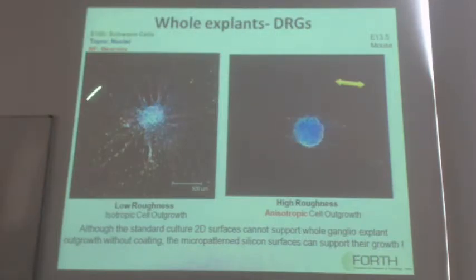You can see here in the low roughness we have an isotropic cell outgrowth of the neurons that can grow out of the explant. It's not very well visible, but you can see it later. Here you can see that in the high roughness surface you can see an anisotropic cell outgrowth. Here is the preferred orientation that is dictated by the micropatterned silicon surfaces under the whole explant.